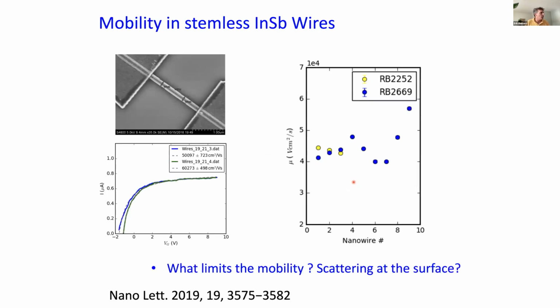So how does that work out for the mobility? To study that, we have fabricated exactly the same devices, with the same channel length, the same thickness of the dielectric, and we have used exactly the same model to fit our transconductance curves. And as you can see here now, we have increased the mobility to about 40,000. So we started at 10,000, then we did pumping, then we went to 20,000. And now by removing arsenic and phosphorus from the system, we have doubled again the mobility,